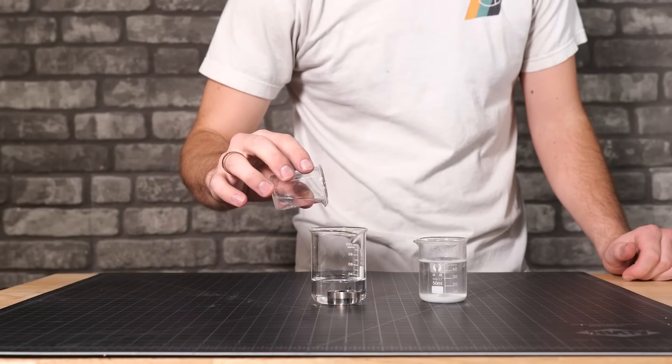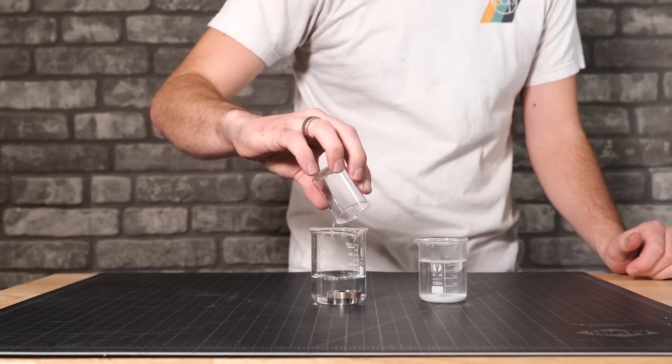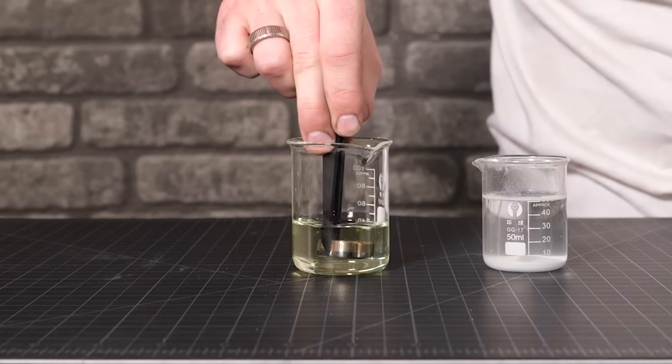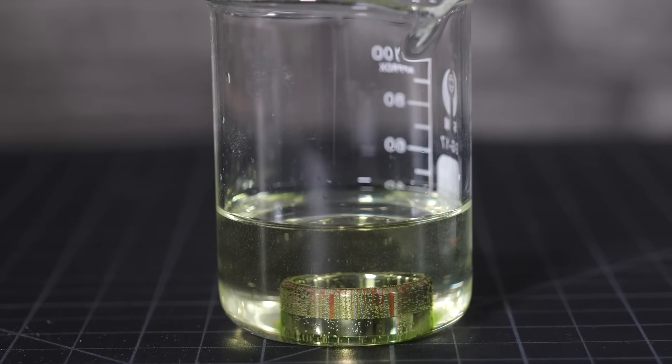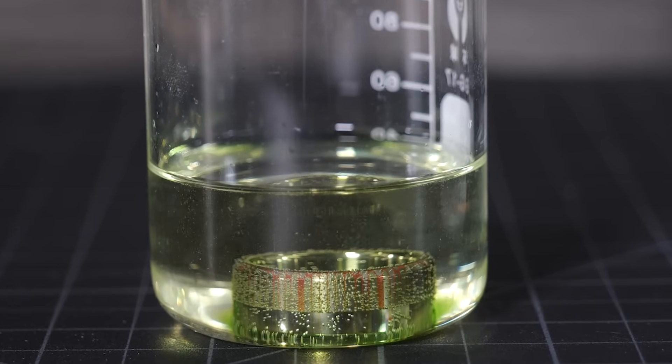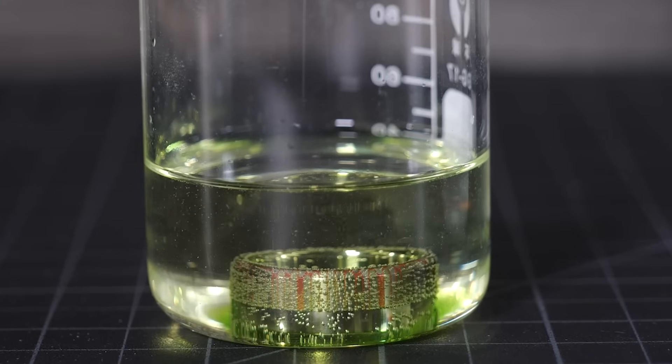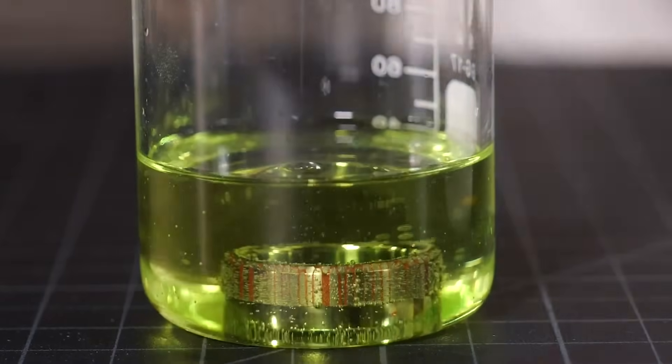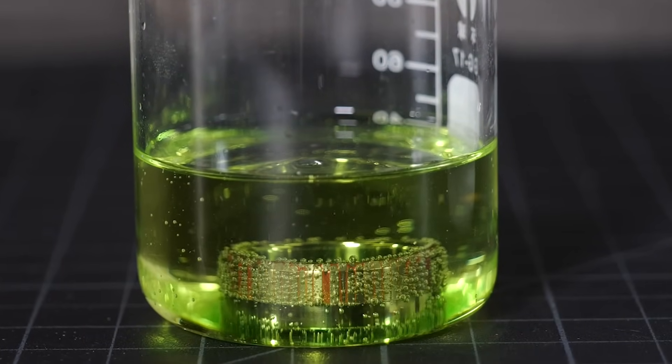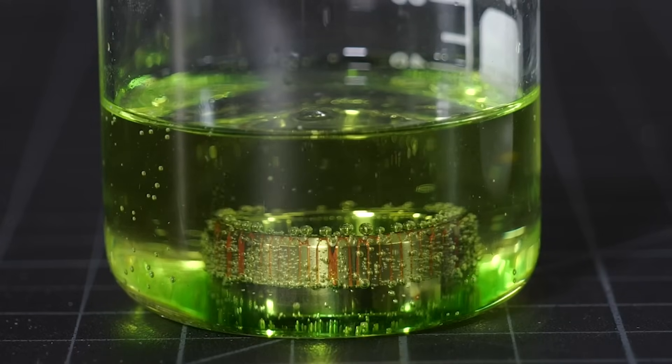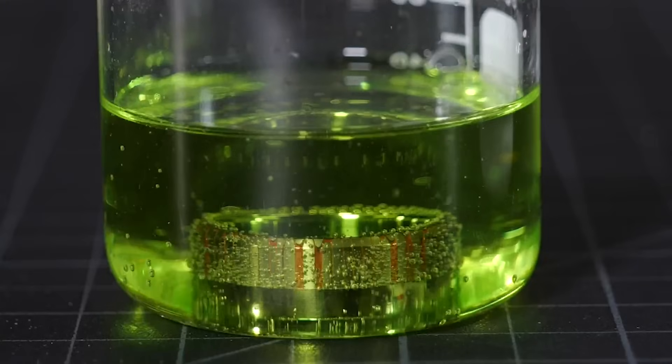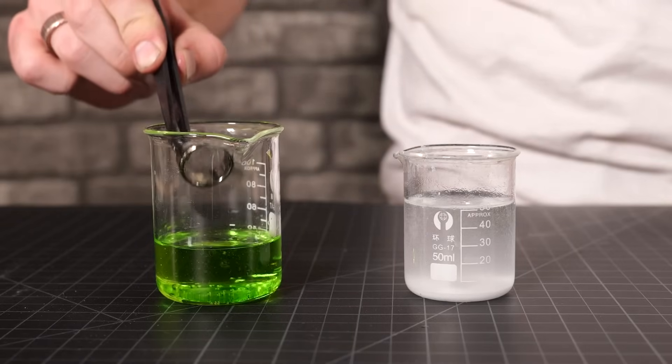Okay in goes the hydrogen peroxide and immediately you'll begin to notice the effects. There's going to be a slight amount of bubbling coming off the copper on the ring and the solution itself is slowly gaining a yellowish greenish tint. And we're going to pull it out before too much copper is removed. We don't want to remove so much that we lose that contrast, otherwise the superconductor filaments aren't going to stand out nearly as well.